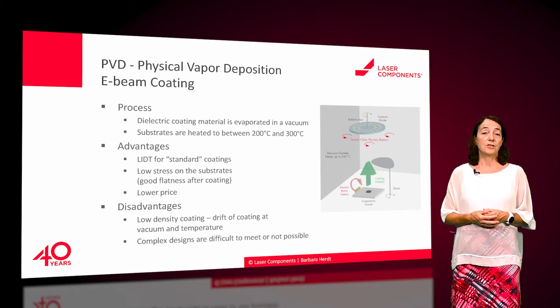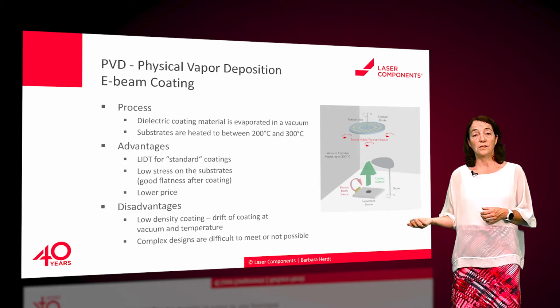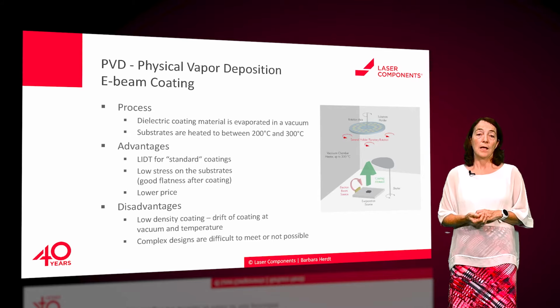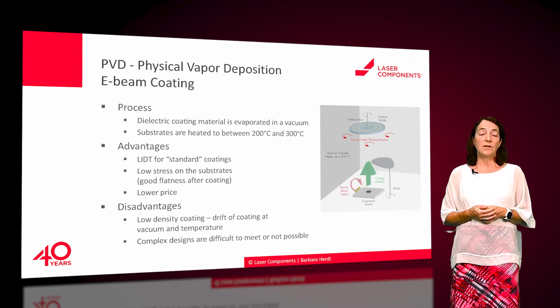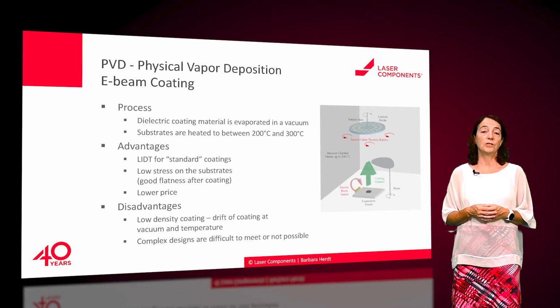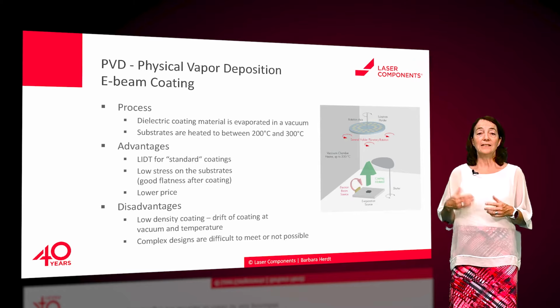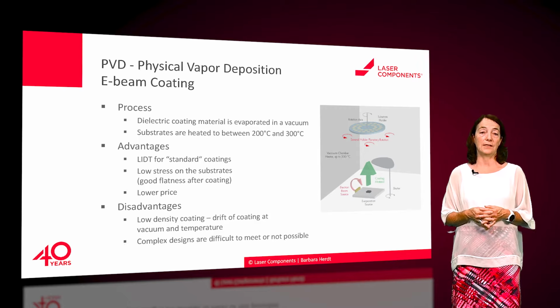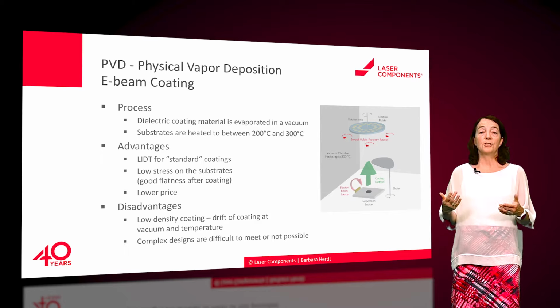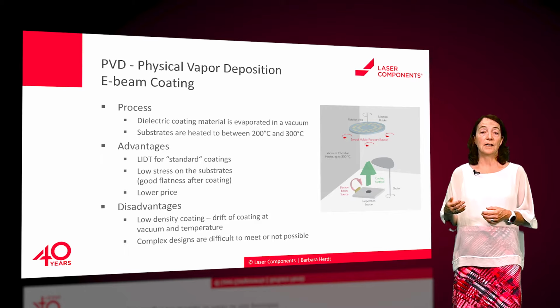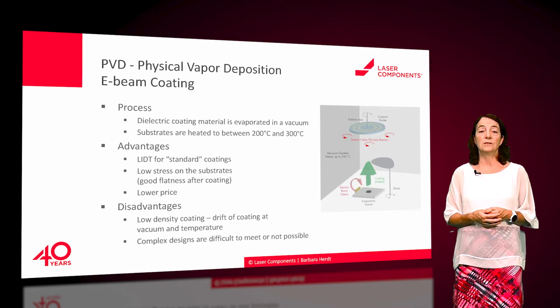Why is E-beam still of interest for many applications? The biggest advantage is the very high damage threshold for nanosecond pulses for standard coatings such as mirrors or beam splitters. This can also be seen in many results at the damage threshold competition, where different suppliers provide samples for LIDT testing with different technologies. As the coating of E-beam is not very dense, the coating has no big influence on the flatness. The other big advantage is the pricing. As the coating time is shorter than for other technologies, the price per coating lot is typically lower.